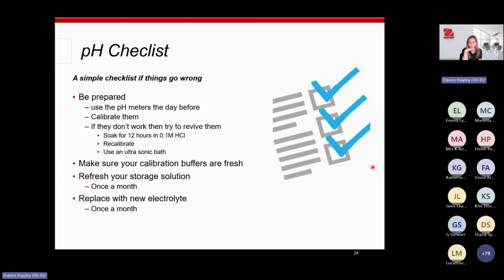Bit of a checklist here. If they don't work, you can revive them in your 0.1 molar HCl for 12 hours. Again, recalibrate. If you've got any that are particularly dirty, you can put that solution into a beaker, into the ultrasonic bath, to really agitate any dirt and grime away from the electrodes. Make sure your calibration buffers are fresh. So they can be fresh out of the bottle, or they can be freshly made up using the buffer tablets. And refresh your storage solution once a month. And also, if you have the refillable electrodes, make sure you replace the electrolyte with fresh new electrolyte once a month as well.